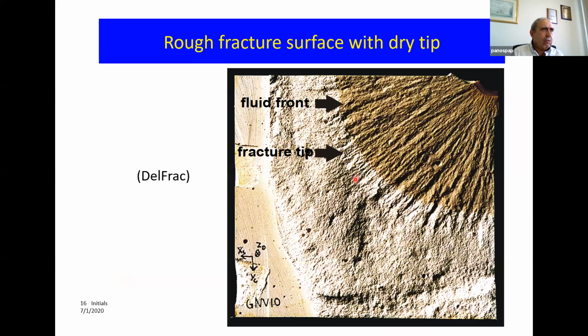And this is one of the pictures actually from the DelFrac consortium, which shows the fracture roughness in the weak plaster. And you can see in this case, in the area where the fracture was propagated, in the wet area and in the dry area, the fluid front is here, the fracture tip here. You can see how rough the surface is, probably due to plasticity.